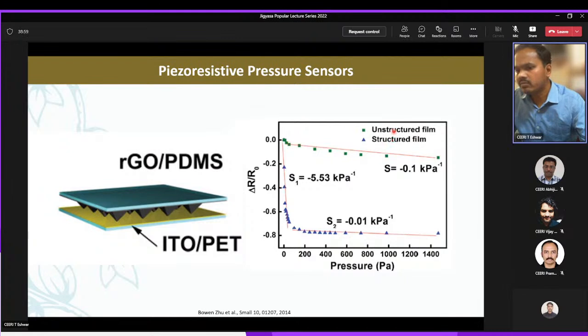For a planar unstructured film, we can see here how the resistance changes with increasing applied pressure. But when these microstructures are introduced, you see that for a given applied pressure there is a huge change in resistance up to less than 100 Pascal. But after 100 Pascal, the increase is very small. So for small pressure, this sensor is very sensitive, with a sensitivity of almost 5.53 per kilopascal. This shows that by microstructuring we can have a more sensitive pressure sensor: the unstructured one is 0.1 per kilopascal, but after structuring it is 5.53. There is a huge increase in the sensitivity. That's why, by microstructuring, a highly sensitive pressure sensor can be developed.